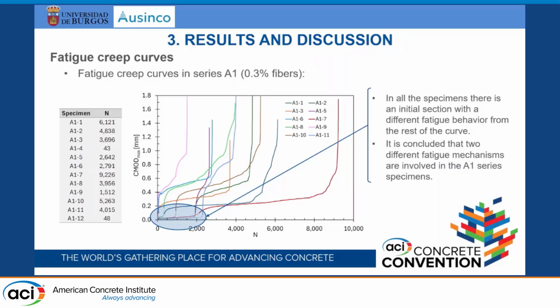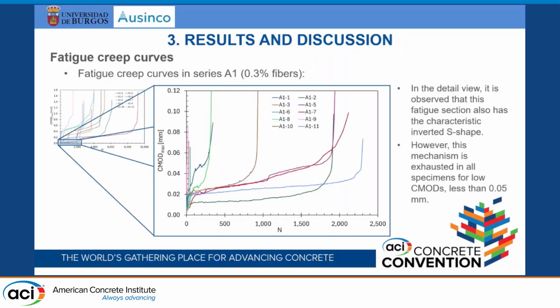If we zoom in over this region, we see that in this small region with very low CMODs, we also have an S curve. There is another different mechanism of fatigue that is happening in the uncracked condition. So that's the main point of that. And obviously, this mechanism is exhausted around 0.05 millimeters, sorry for the units, which is more or less the region in which fiber reinforced concrete matrix usually cracks, right?